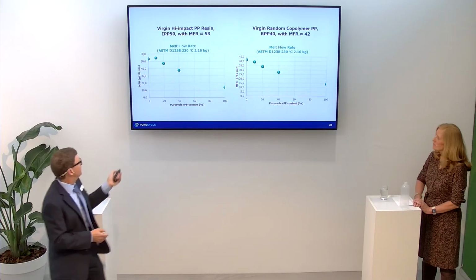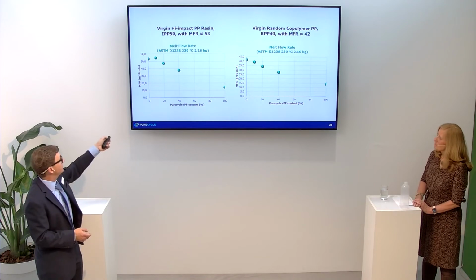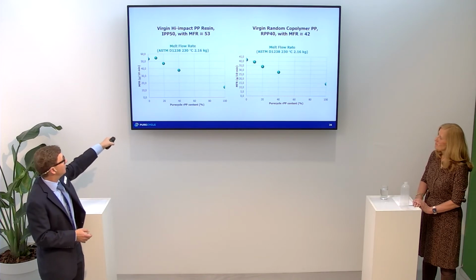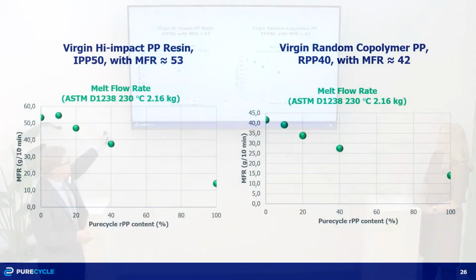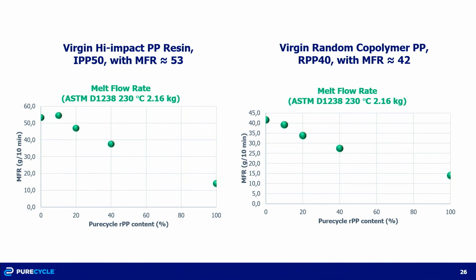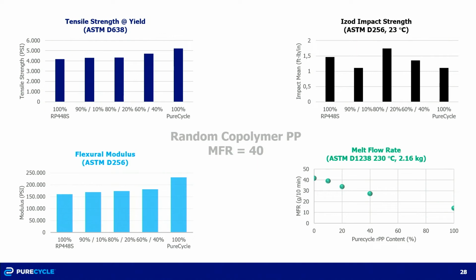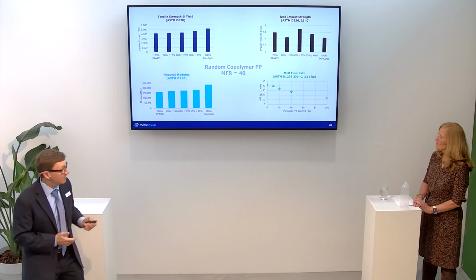This is getting to the higher melt flow range, blended with a 50 melt flow impact copolymer. And you can see that the trend is relatively linear as you blend and meet the right melt flow specs. And the data will be shared later.